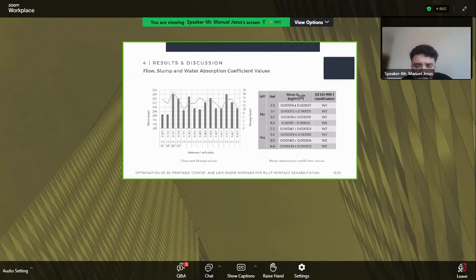And as you can see, formulations 3.1 and 4.2 recorded the lowest slump, demonstrating superior cohesion and structural resistance that is required for high-performance 3D printing. Now, regarding the water absorption by capillarity. This test was conducted over a 24-hour period to evaluate the water infiltration on each composition.